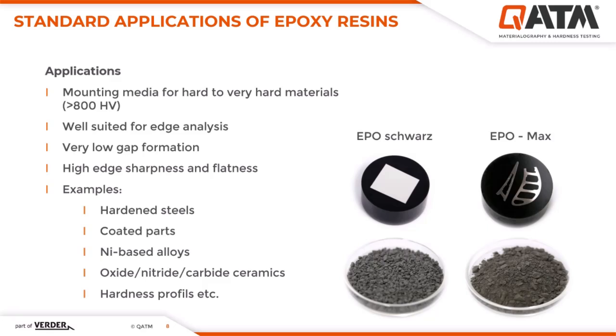Epoxy resins are often used when very hard materials need to be prepared, meaning materials with a hardness greater than 800 HV. They are also used for edge examinations where low gap formations and high edge sharpness and flatness of the sample are important. Typical examples include hardened steels, coated parts, nickel-based alloys, ceramics, or samples where hardness profiles need to be measured.